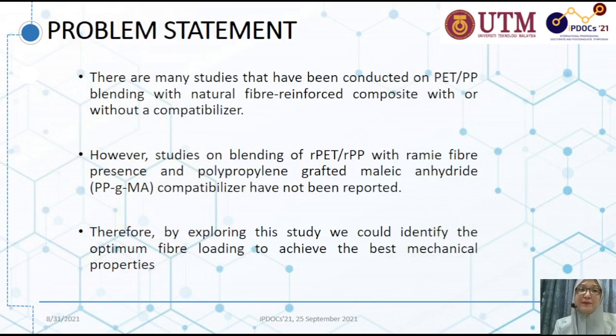So for problem statement, there are many studies that have been conducted on PET PP blending with natural fiber reinforced composite with or without compatibilizer. However, studies on blending of recycled PET and recycled PP with ramie fiber and polypropylene grafted maleic anhydride (PPGMA) compatibilizer have not been reported. Therefore, by exploring this study, we could identify the optimum fiber loading to achieve the best mechanical properties.